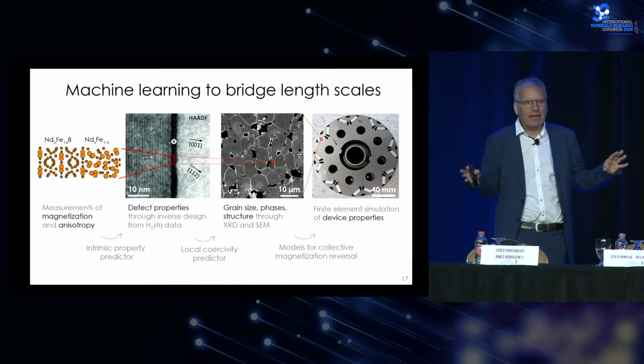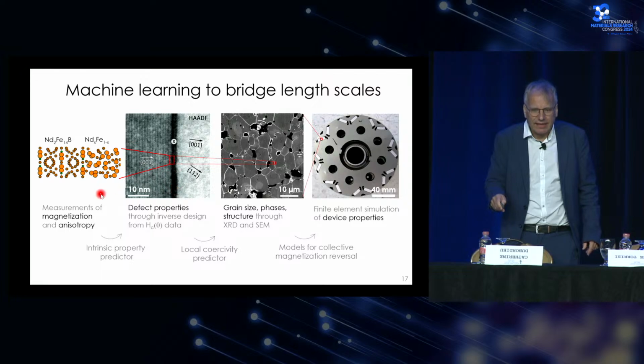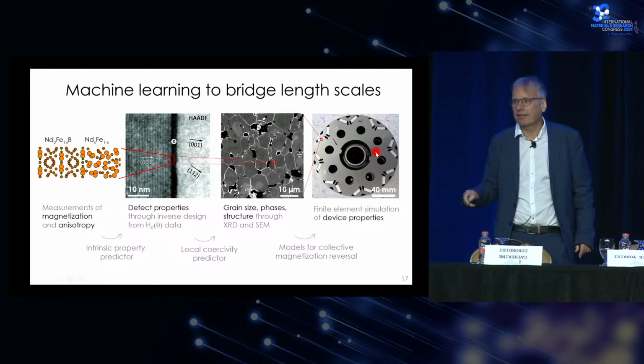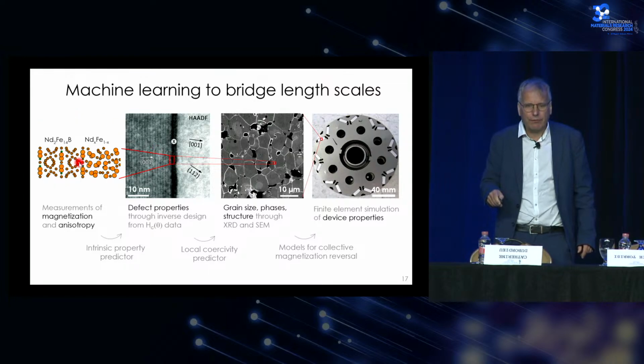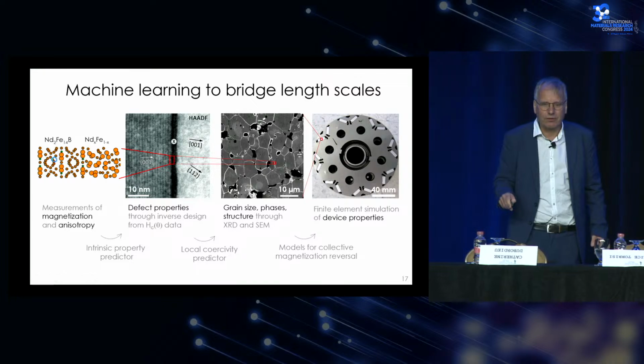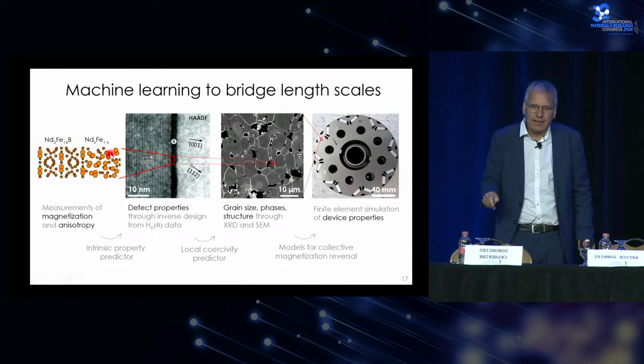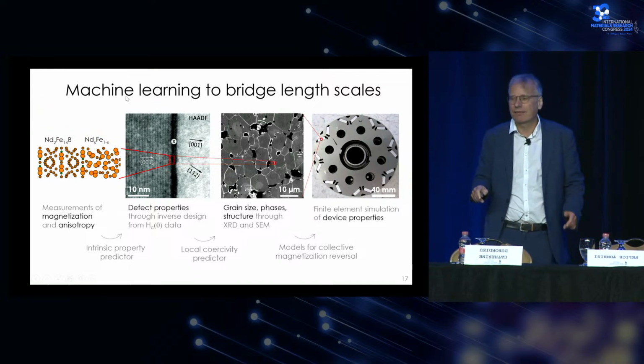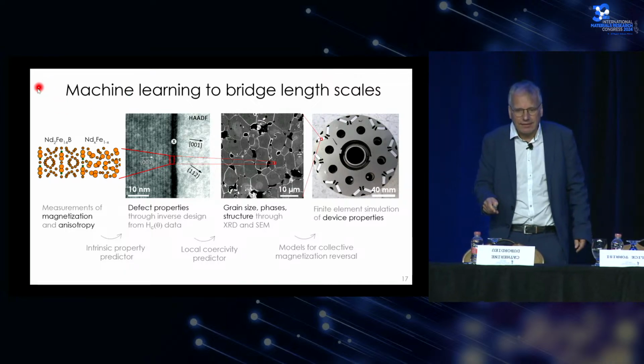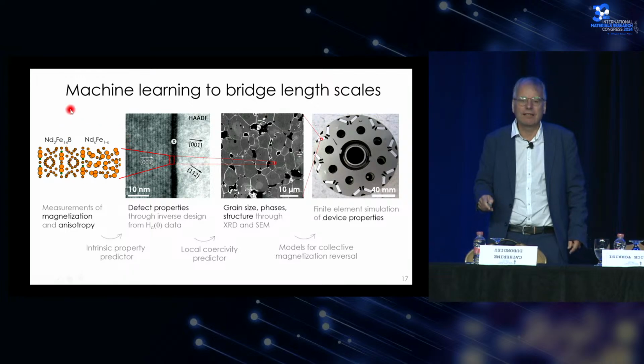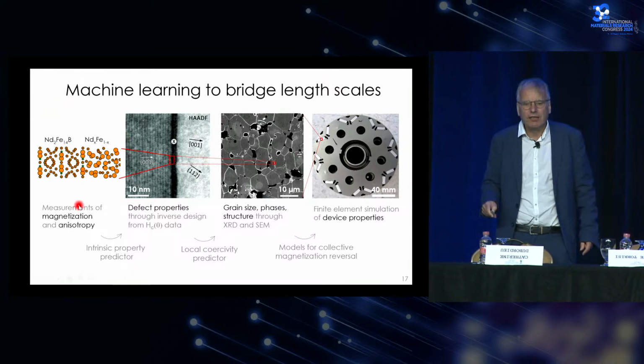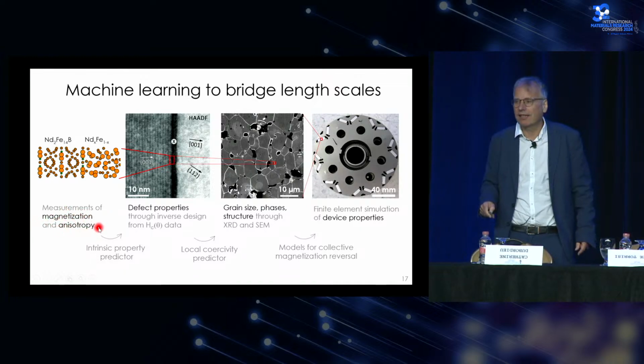If we talk about magnets, we immediately see that we have to understand the properties at very different length scales. On the very left, we have the atomic structure of the materials. So for example, if we go to neodymium iron boron, we have 68 atoms in the unit cell, and we know the arrangement of the atoms. And then this main neodymium iron boron phase is located next to a grain boundary phase with certain properties. And the atomic arrangement of the material and the atomic chemical composition determines the magnetization and the magnetocrystalline anisotropy of the material.